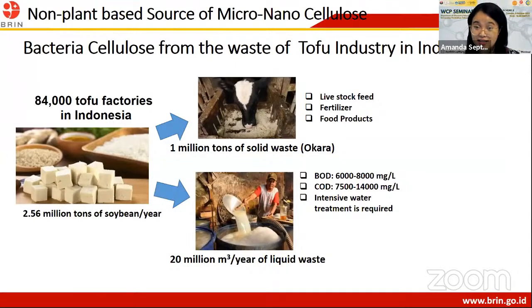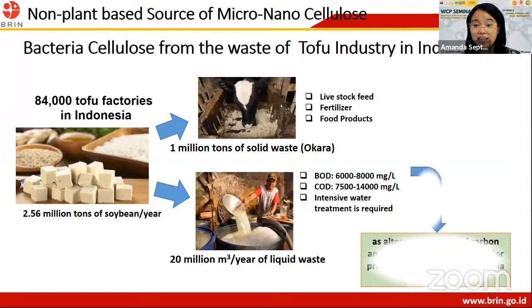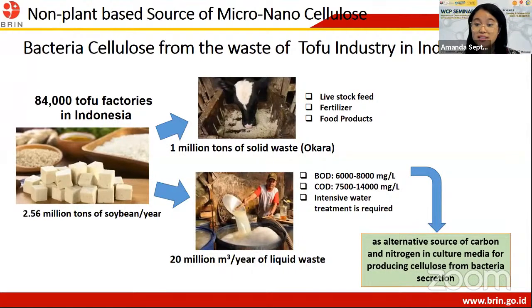In fact, this liquid waste is about 20 million cubic meters per year, containing high BOD and COD. Even the color itself is cloudy, which influences the quality of water. So intensive water treatment is really required to utilize and reuse the waste from the industry in terms of the liquid waste. In fact, this liquid waste is an alternative resource rich in carbon and nitrogen. And from these rich resources, we can actually produce cellulose from bacterial secretion.